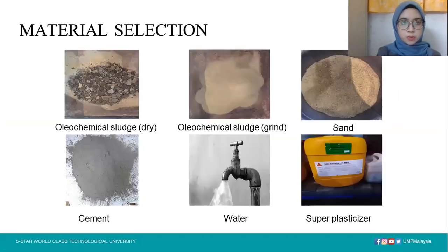Now we will proceed to the material selection, which includes oleochemical sludge. This is oleochemical sludge before grinding, and we have oleochemical sludge after grinding, sand, cement, water, and also the super plasticizer in the mixing. SP super plasticizer is used at about 0.7. The water cement ratio used is 0.5, and the ratio of cement to sand is 1 to 6.